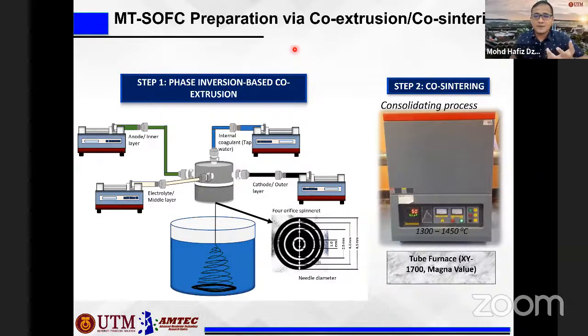First is the phase inversion based co-extrusion technique. Instead of having one ceramic suspension extruded through the spinneret, if you would like to have a 2-layer or 3-layer, you have to multiply it. Meaning that you can inject the electrolyte layer and also the cathode layer simultaneously in order to produce the triple or dual layer. So this is the spinneret that we have, a four orifice spinneret, in order to produce a triple layer hollow fiber membrane. And then we can co-sinter them together. By having this step, we only need to use one sintering process.